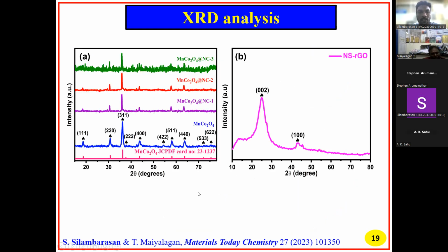In XRD analysis, in MnCo2O4, the 2 theta is around 35.6, and the plane is 311. Compared to nitrogen doped carbon composite 1, composite 2 and composite 3, the peak intensity slightly decreases and there is a slightly negligible shift. But the carbon peak is not shown here because the carbon has an amorphous nature.